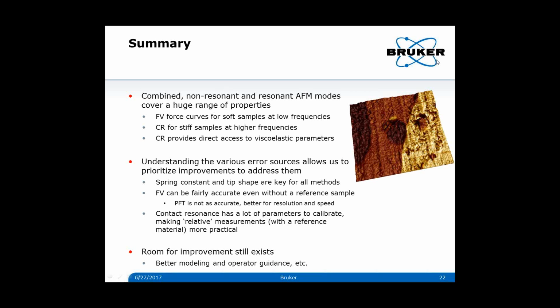And Bede, you mentioned cleaning the tip. How would one clean a tip in your system? So one way to clean a tip would be to scan a sample that has a lot of sharp edges on it. The tip check sample is one sample that will have a tendency to remove soft material from the tip. The tips that we are working with, these 30 nanometer end radius tips, are robust enough that they can scan the tip check sample without being damaged themselves, and just the contaminant gets removed from the tip during that process.